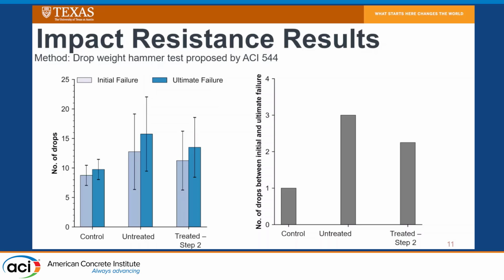We can see that when we look at our control versus our untreated and our treated specimens, we get this increase in the number of drops. So that means that it takes more energy in order to bring our samples to failure, right? And then when we look at the gray bars, this is showing you the number of blows that it takes to go from your first crack, so that's initial failure, to the ultimate failure. And we see that when we compare the control to the treated samples, once we include rubber inside of it, we get this increase in the number of drops. So this indicates that we get this increase in toughness.